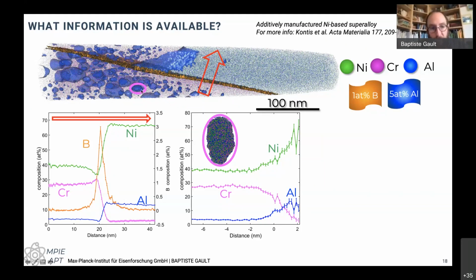And then based on the position of the polygons that surround this particle, I can look at the way the composition varies as I move out and expand this surface, and then when I move in and compress this surface. And in principle, this gives me the composition that evolves away from a particle that cannot really be fitted easily with a cylinder or cuboidal region of interest. So that's often what we see in papers. The problem associated with this is that we're starting from a grid, a series of voxels. So we are losing a little bit in resolution. So the resolution is poorer in the voxel method compared to the cylinder.